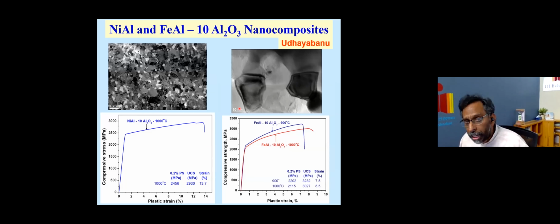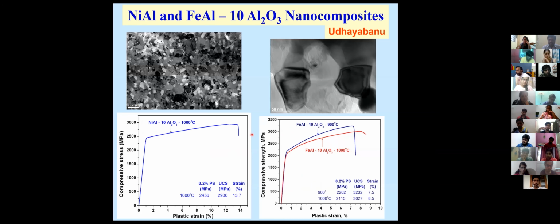For example, if I take nickel oxide and reduce it with aluminum, I get nickel and alumina. If I control my composition carefully, I don't get just pure nickel. Nickel plus aluminum, a compound called NiAl, I get, and I get alumina as a product. So both of them form a composite now. You have NiAl, you have alumina, and it's called a nano composite because both of them are in a nano state. Such a material has very good strength and very good toughness, because its compressive strain is very large.